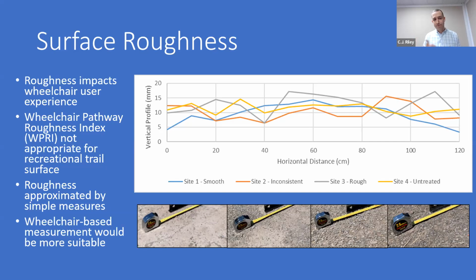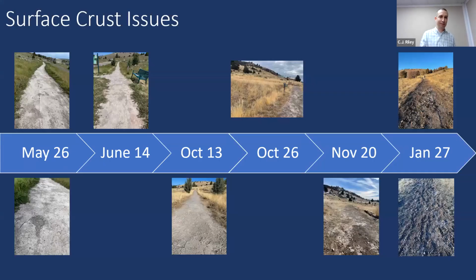So for a variety of reasons, we didn't measure this, but we did go out to try and measure relative elevations along the length of this and kind of get around the aggregate. And you can see the blue line here is relatively smooth location to location. We took measurements every 10 centimeters, so you can see where those kinks are. The changes in elevation are relatively small, but as you get into the rougher and even the untreated material, you can see where those changes in elevation are more significant. So it was pretty clear that we had made improvements in smoothness.